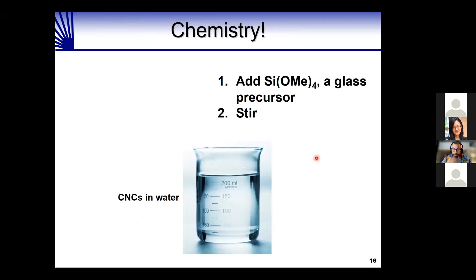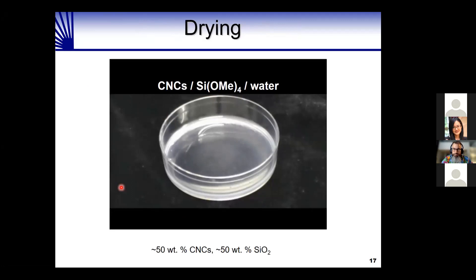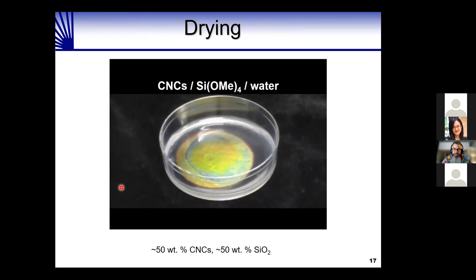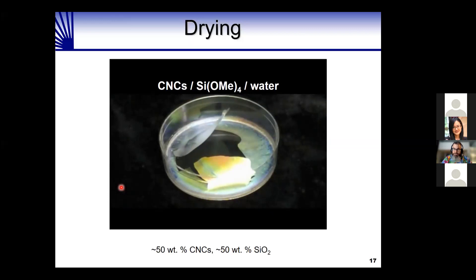Here's our chemistry: we take a beaker of cellulose nanocrystals in water, add tetramethoxy silane, stir it, and transfer it into a petri dish. Then we let the water evaporate overnight. This is a video of the water evaporating, and you can see the color magically appear as the cellulose nanocrystals organize into the helical structure. This tells us the chiral nematic structure is forming, while at the same time the tetramethoxy silane is condensing around the nanocrystals to give silica.